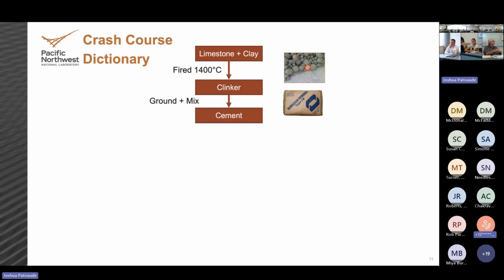So they'll take these nodules, grind them up into a fine powder, and then mix it with some other chemicals. The other chemicals you can add in are aluminum sources, lime, and magnesium sources to tailor the resulting cement powder for a specific application. So there are a number of different types of cement. The most common ones are type 1 and type 2 Portland cement, which is now essentially type 1L cement, Portland lime cement. So you would add those additives to get specific properties in your final material, but again, also to save cost.